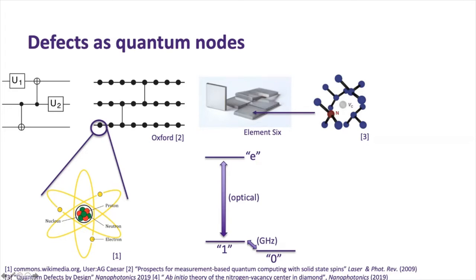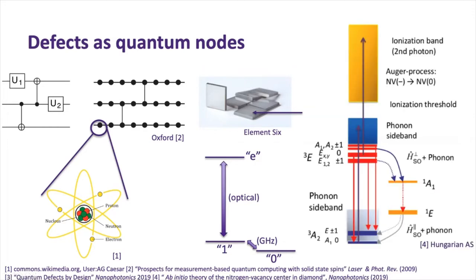Of course, just as with atoms, life is a bit more complicated. And here you can see what's known about the nitrogen vacancy center, the negatively charged nitrogen vacancy center energy level structure. And it is quite complicated. There's many, many more levels than the simple three-level diagram that I show here. And there's also interactions with lattice vibrations or phonons. But what we can do is still spectrally isolate and address three levels in this diagram in order to do the types of protocols that I'm talking about.